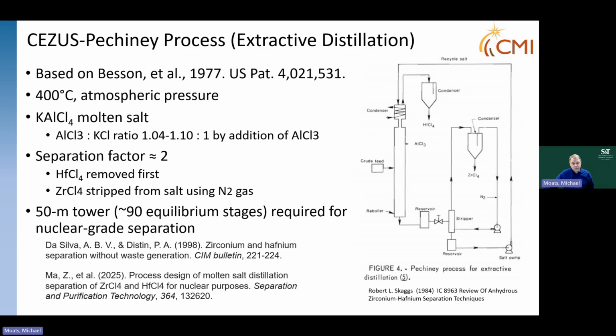The aluminum trichloride is actually lost in the process a little bit, so you have to add it to keep this ratio the same. Basically what happens is in this molten salt, the hafnium volatilizes and the zirconium gets absorbed into the salt. Zirconium comes out the bottom and hafnium comes out, and then we go through the cooling stage like we always do to get this hafnium tetrachloride salt back. The zirconium that comes out, they actually blow nitrogen gas through the molten salt because zirconium tetrachloride has vapor pressure, just not as high as the hafnium tetrachloride. And so again, it comes up and we condense it.